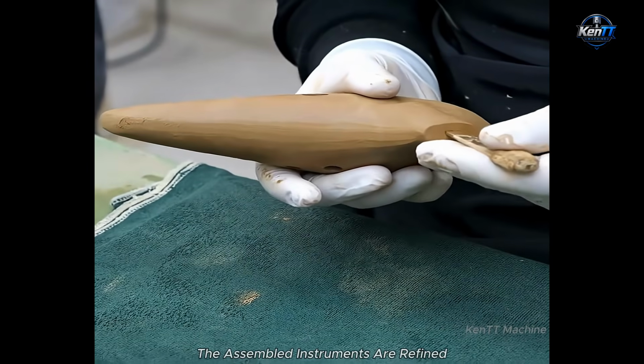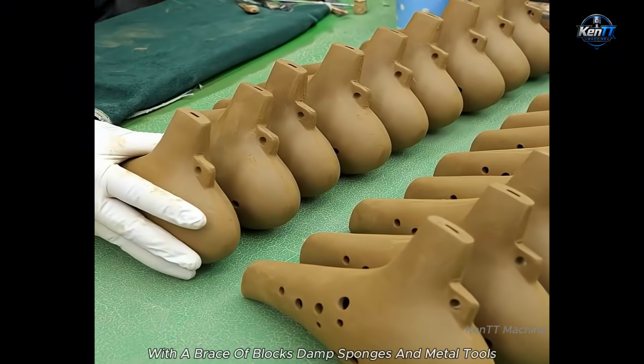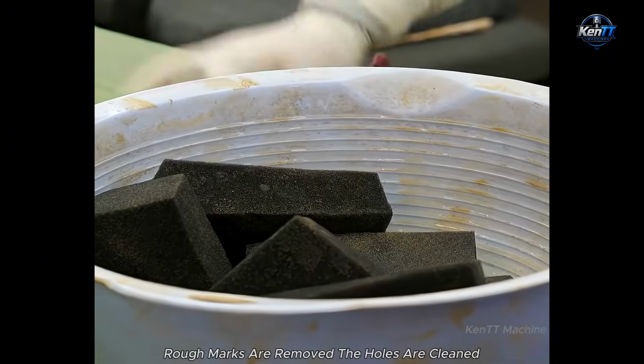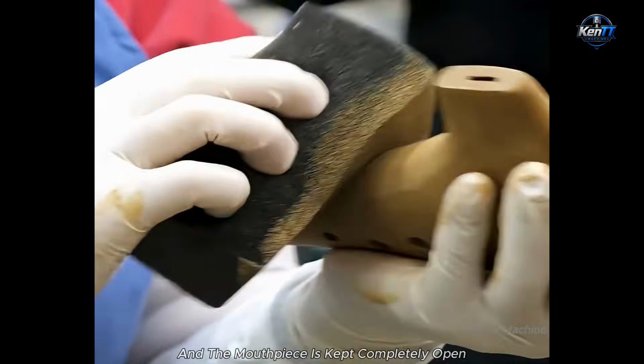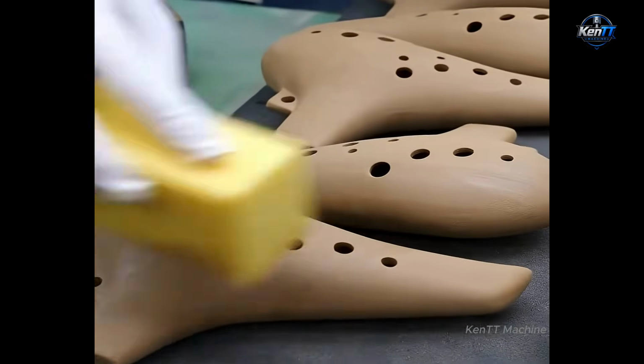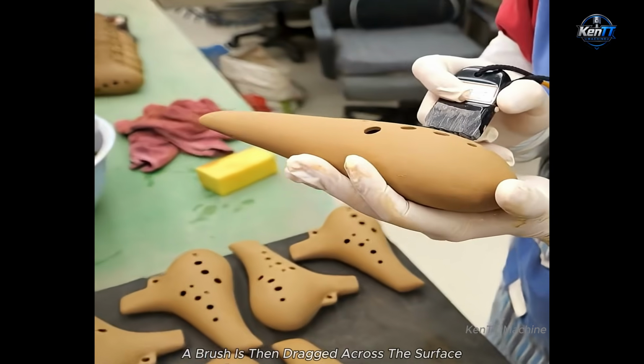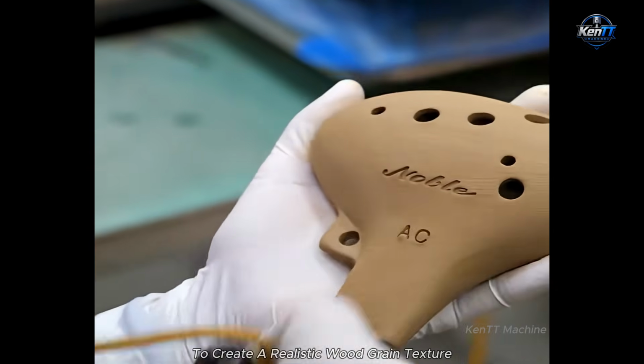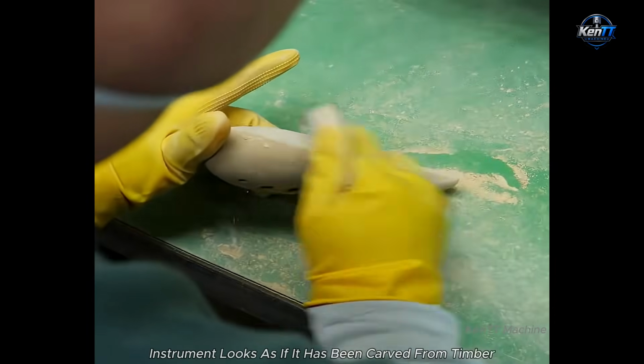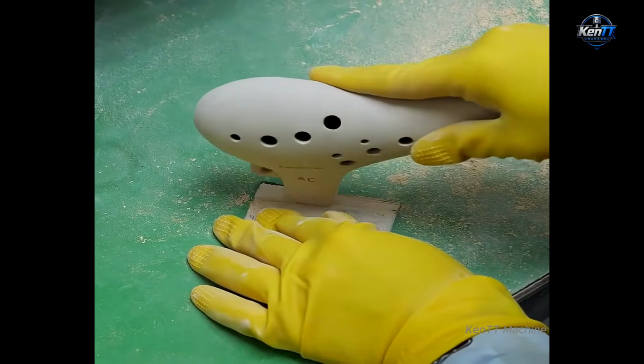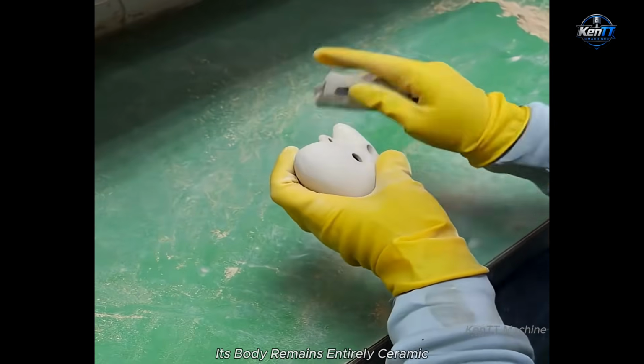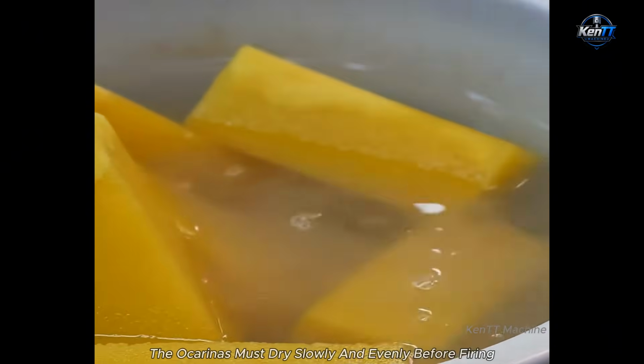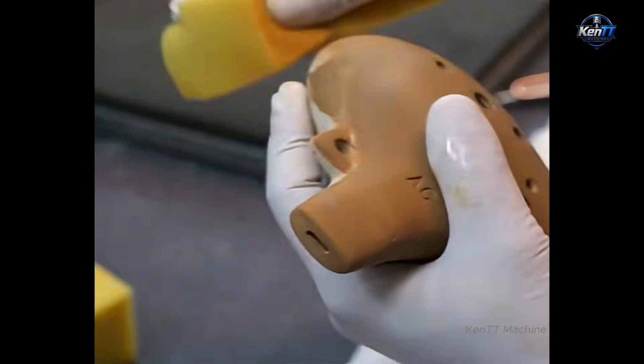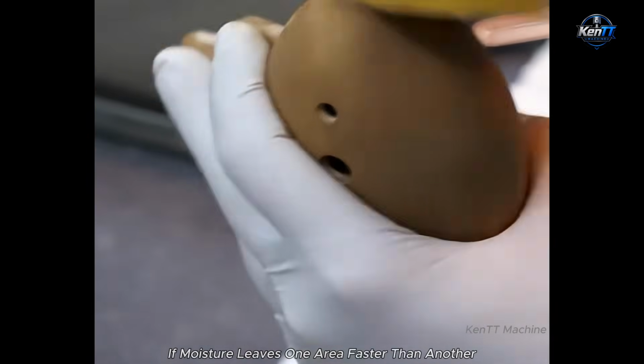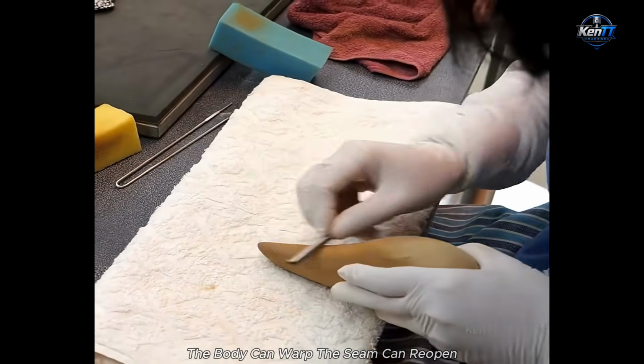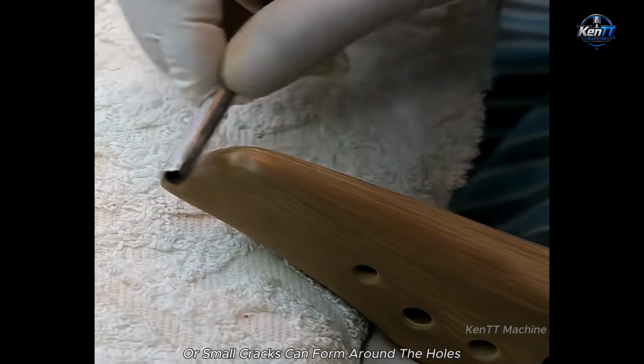The assembled instruments are refined with a brace of blocks, damp sponges, and metal tools. Rough marks are removed, the holes are cleaned, and the mouthpiece is kept completely open. A brush is then dragged across the surface to create a realistic wood grain texture. Although the finished instrument looks as if it has been carved from timber, its body remains entirely ceramic. The ocarinas must dry slowly and evenly before firing. If moisture leaves one area faster than another, the body can warp, the seam can reopen, or small cracks can form around the holes.